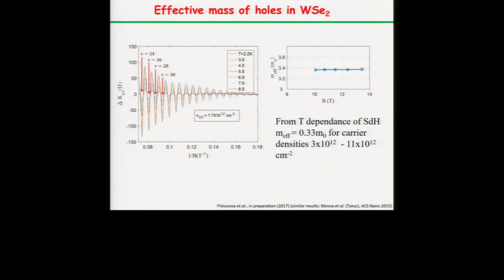And we also can obtain the effective mass, as it has been done also by others in the literature. We obtain the effective mass by measuring the temperature dependence of the Shubnikov-de Haas oscillations, and we obtain a fairly flat effective mass for a large range of carrier density. So it's around 0.33 the rest mass of the electrons.